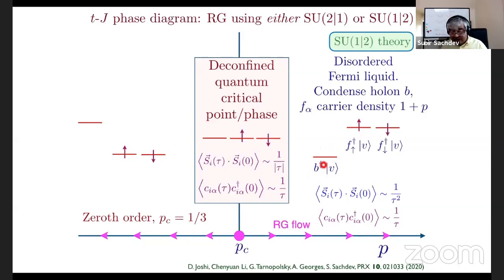Well, if you condense the holons, then these F become the electrons, and you break the U1 symmetry, and in fact the density of these F is the density of electrons, and therefore this is exactly a Fermi liquid. It's a disordered Fermi liquid, and then you can see easily that the spin correlation now decays as 1 over tau squared, whereas this decays as 1 over tau.